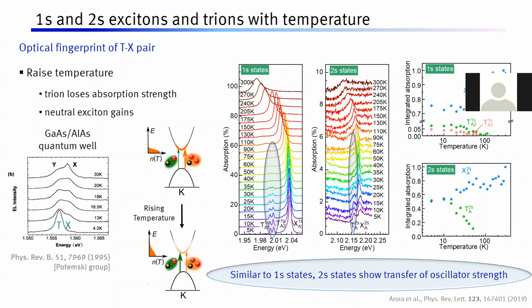Yeah, so essentially the oscillator strengths of various signatures due to defects are always very small, always. So you will not normally see the effect of defects in absorption spectra. You will see them in luminescence spectra. This is what people see as well. There are some defect-based peaks in some materials which are very low in energy, and they appear only in luminescence. However, this is not a bulletproof case of what I am trying to say.